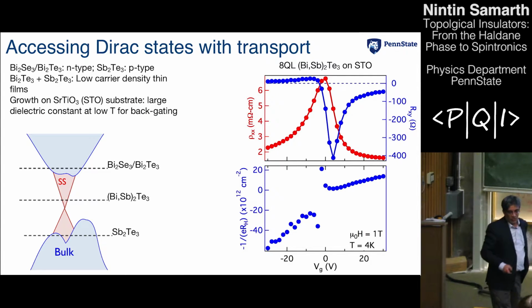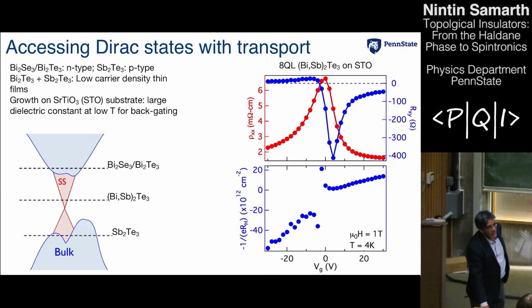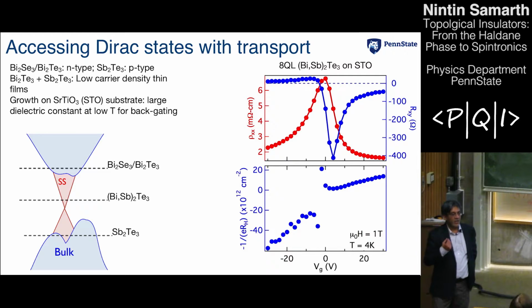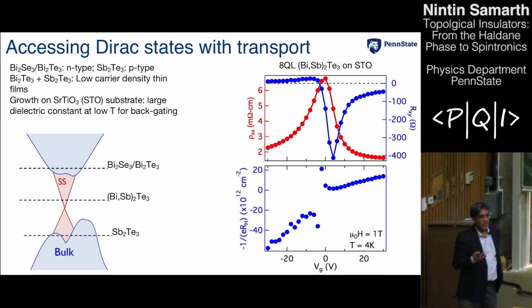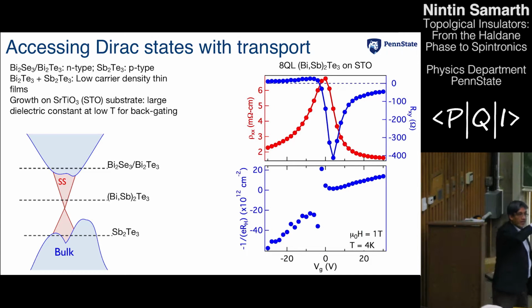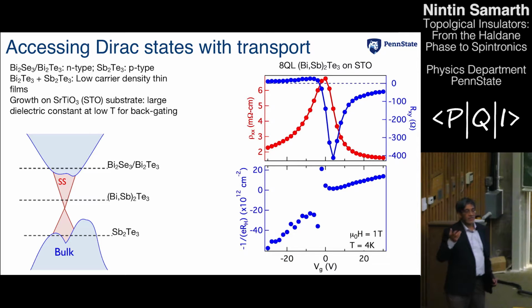Now, as I mentioned, one of the problems that we face in making these thin film samples by the technique that we use, molecular beam epitaxy, is that there are these selenium vacancies that are formed. So these are not perfect crystals or great materials, as Sarah was mentioning. They are riddled with defects. And the prominent defect is really the selenium vacancy. Now, what one would like to do is do measurements in which you're dominated in electrical transport by these surface states, and you don't have conduction anywhere else. But with these selenium vacancies, it's a problem.